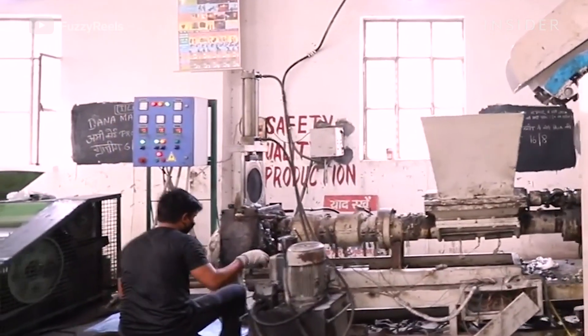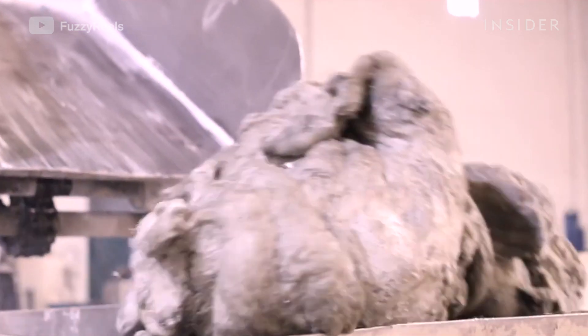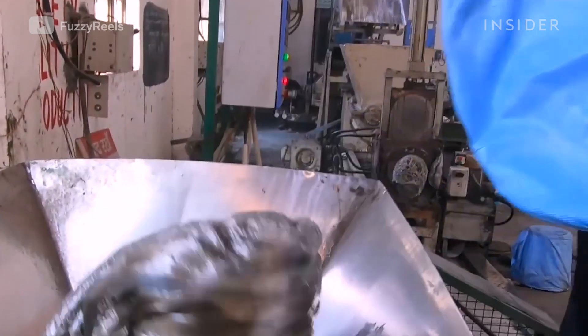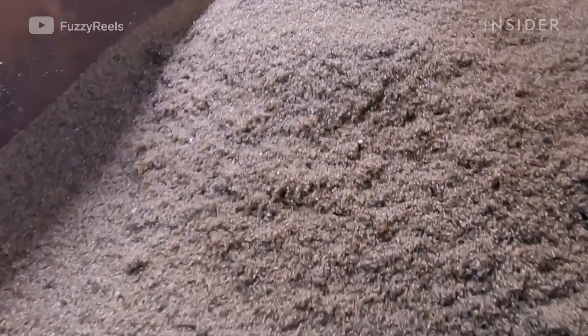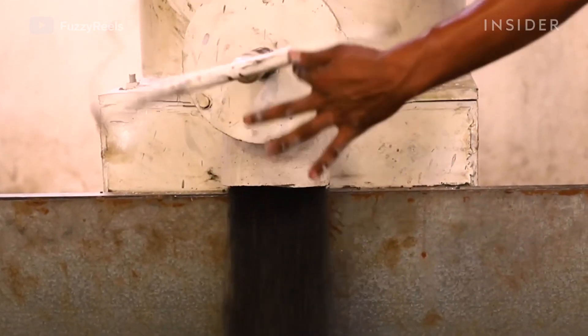The recovered PVB is thrown into what's known as a Banbury mixer, which is basically a kneader machine. Depending on the product it's to be used for, a batch of PVB is mixed with specific chemical additives, polymers, and rubbers, while heat and pressure are applied to knead it all together into a doughy substance. The doughy mixture is then fed into an extruder machine that uses screening and filtration tools to remove any last bits of contamination. A second extruder is used to form the PVB mixture into granules or pellets, which are blended with chemical agents for drying, releasing mold, and removing any odor.